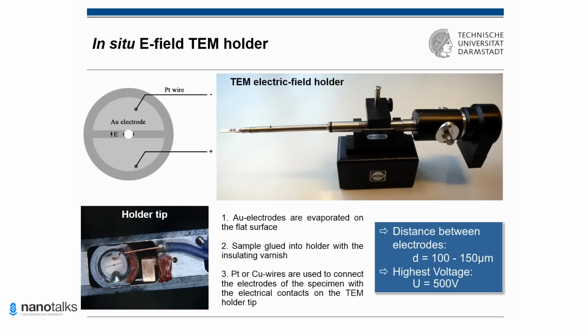Yeah, okay. So this holder works for this kind of experiment. That's why we use it, of course. But the main challenge is experimental difficulties. For instance, to glue these wires, which in our case, most of the time I used, were platinum wires, 50 micrometers, it's very difficult to glue them by hand to the sample, and to glue the sample to the holder. And from my experience, out of 10 experiments, successful was maybe half of that in the